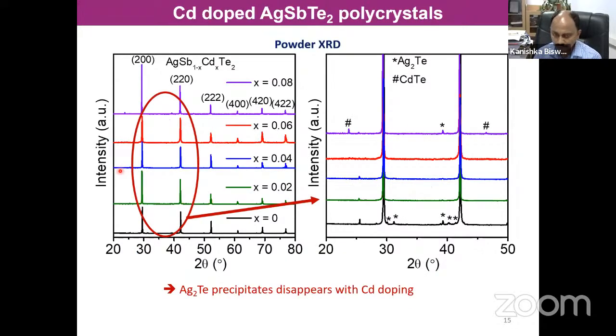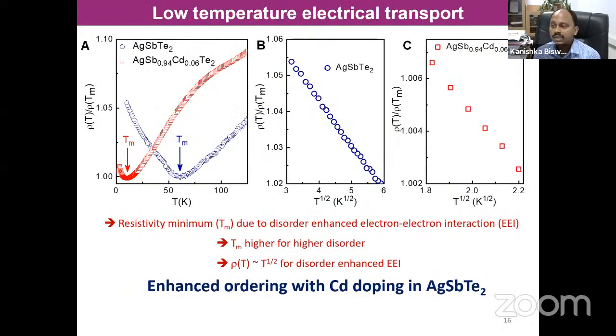So let's see what happened. We measured the low temperature resistivity, which is an indicator of localization or delocalization in this kind of solid. For example, this is AgSbTe2. When you measure the low temperature resistivity, it shows an upturn and a minimum. When this kind of minimum comes, it gives a direct signature of localization. Fitting this low temperature data gives a root T dependence, which tells that this is nothing but enhanced electron interaction.